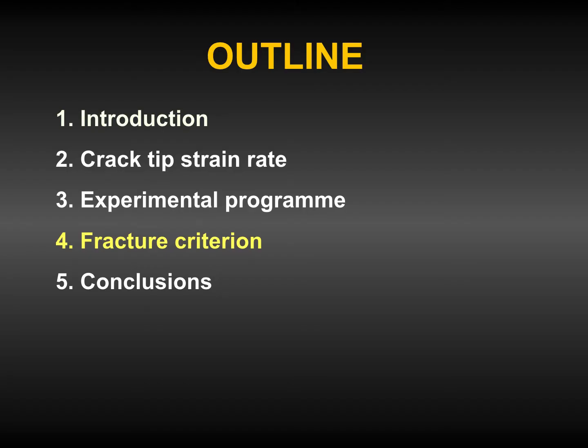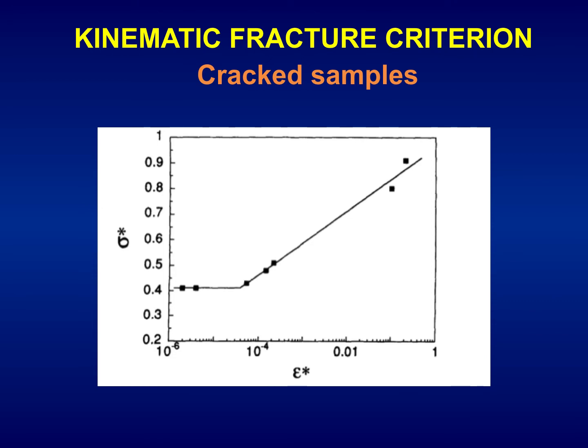Then let's formulate a fracture criterion on the basis of the local strain rate at the crack tip, or local strain rate in the vicinity of the crack tip, the so-called crack tip strain rate, CTSR. This is a sort of kinematic fracture criterion on the basis of this local crack tip strain rate. This kinematic fracture criterion for cracked samples is formulated by using two dimensionless variables plotted one against the other: the dimensionless stress sigma asterisk and the dimensionless strain epsilon asterisk. Sigma asterisk is computed on the critical load in the hydrogen-assisted cracking test, normalized